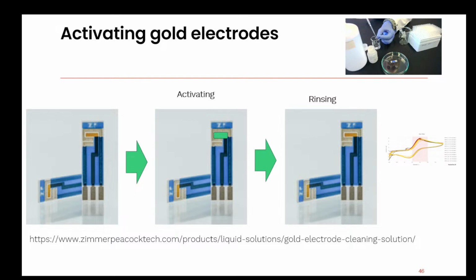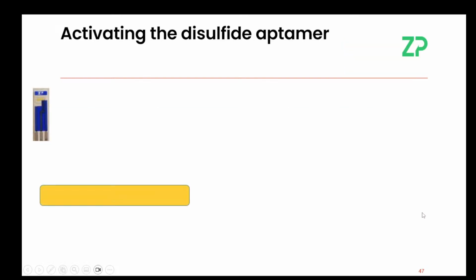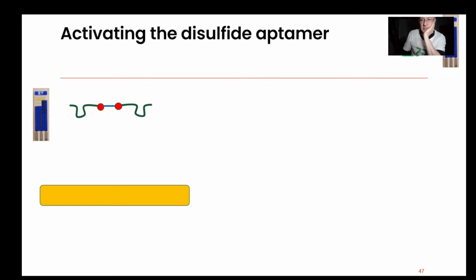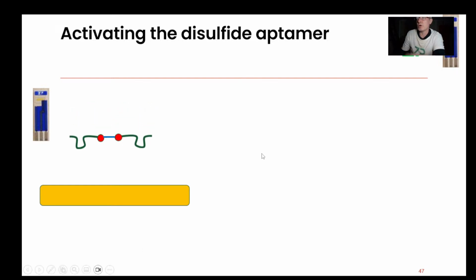Even if we've done that quality control, even before we start the functionalization, we actually activate. But we then don't leave these electrodes hanging around. We immediately use them. You asked the question whether you should just essentially split this disulfide bond using TCEP, and I think the answer is not whether you should, it's that you should. Otherwise, you've got a process where you're relying on that gold to split that bond. So it's slightly out of your control.